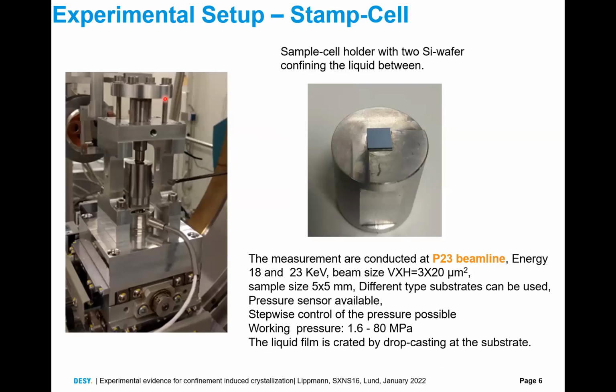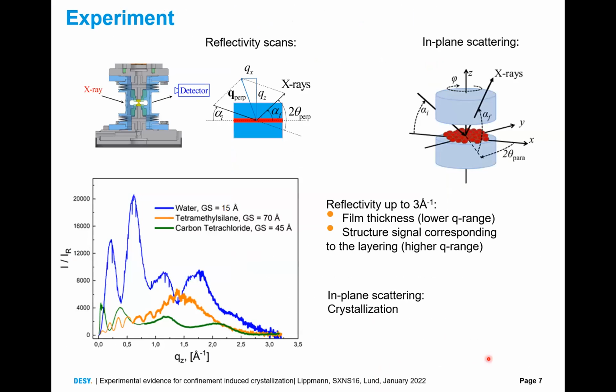The other cell is the so-called stamp-cell. Here we can confine the wafers, 5 by 5 millimeters, and we compress them with the stamp on the top and measure the pressure with the pressure sensor on the bottom. And here the liquid films are created by drop casting.